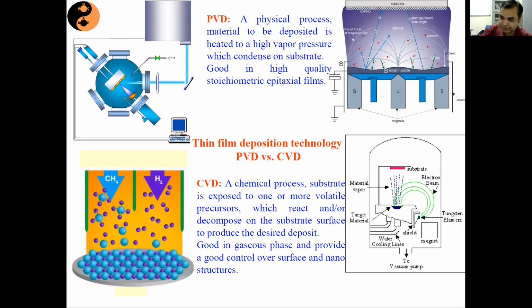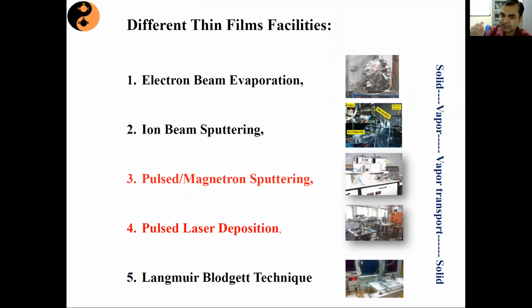So there are different ways of transferring the energy to the target material, and accordingly we have different techniques to grow these thin films. If we are using thermal heating, then we call that technique thermal evaporation. If we are using electron beam bombardment to overcome the bond energy or to get the evaporation done, we call that technique electron beam evaporation.